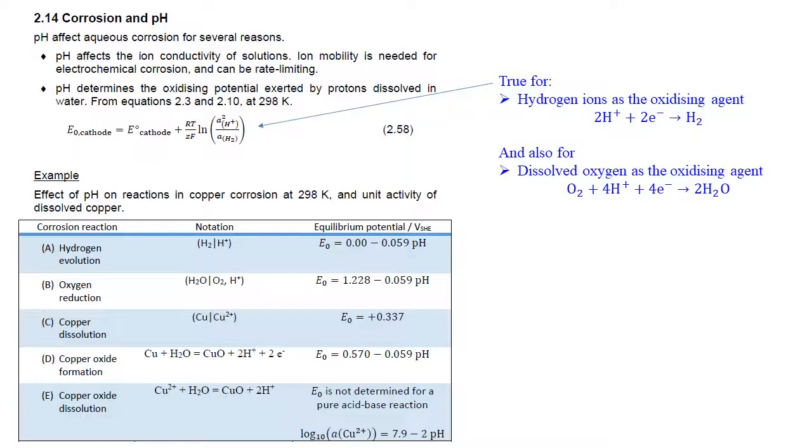First question, does the solid metal dissolve into ions? That would take place by pure electron transfer or redox chemistry. That's controlled by mixed surface potential. Second question, does the metal oxide or hydroxide or whatever dissolve into solution? That would be by proton transfer or acid-base chemistry.